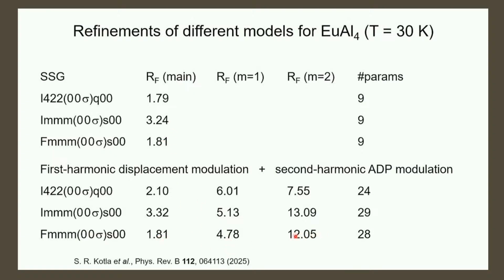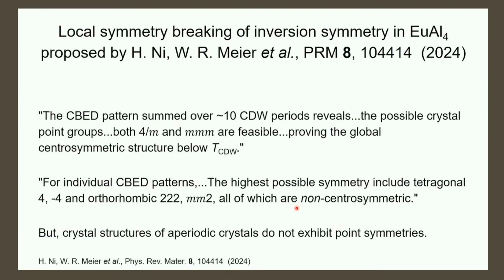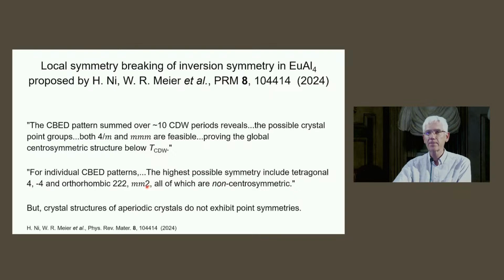This is good, that's not so terribly good, but many structures have been published. Then came this paper by Ni, Meier and co-workers, convergent beam electron diffraction, and they had some argumentation of a global centrosymmetric structure and point symmetry of the structure, which are not appropriate for this incommensurate structure because there is no difference between global and whatever structure. There is a crystal structure which is incommensurately modulated, and there is no point symmetry.